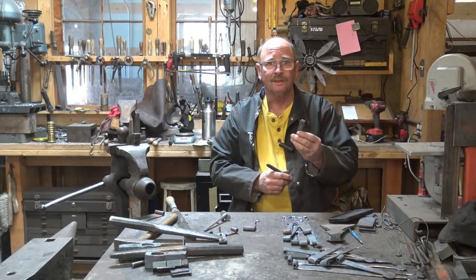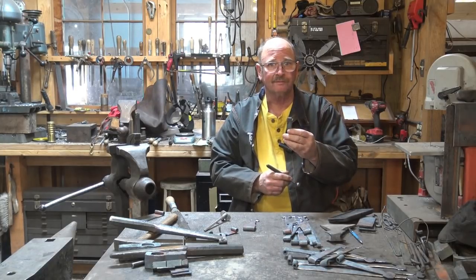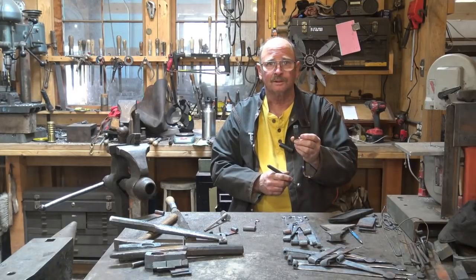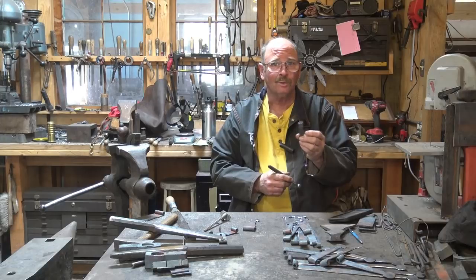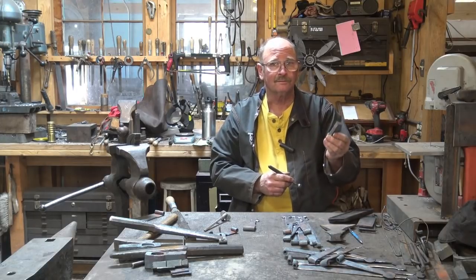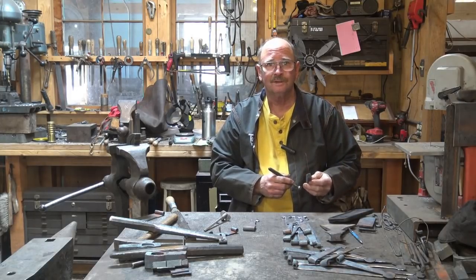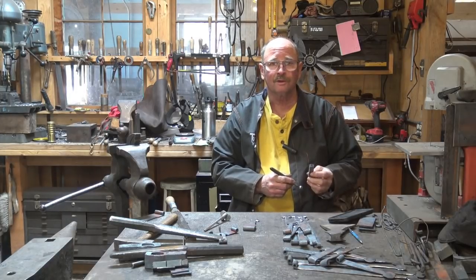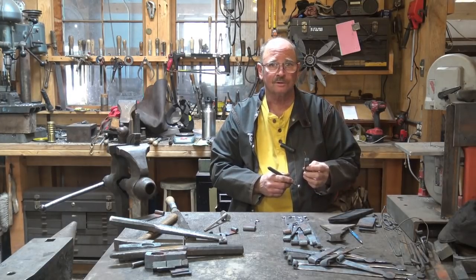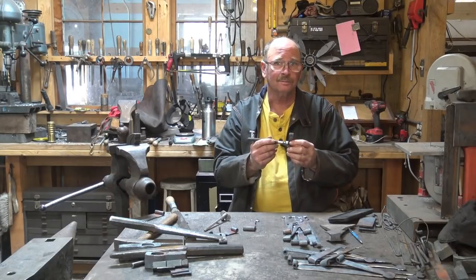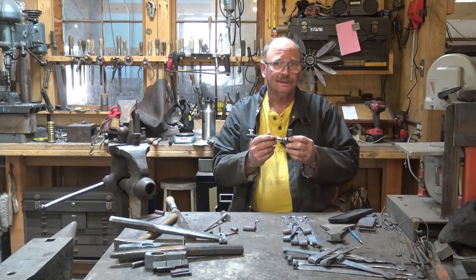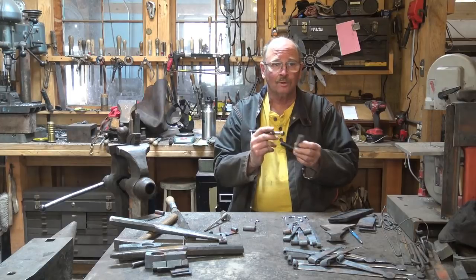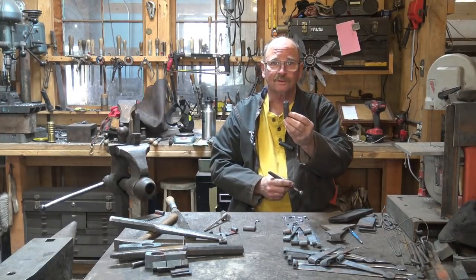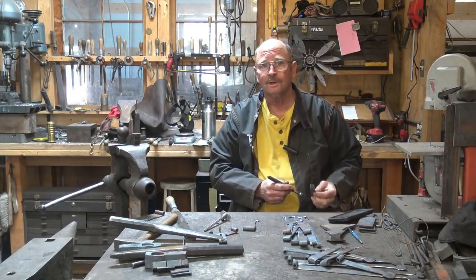This W1 I think is 1475, and I have all this written down, so we'll take a look at it. And something like H13 is something like 1825. So that's 350 degrees difference in the range of what that critical temperature is for hardening. So if you just brought H13 up till it loses magnetism, is it at 1800 degrees or is it at the 1475 degrees that it is for the W1?